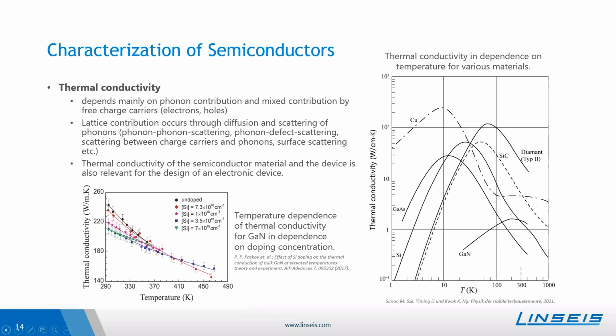In general, the thermal conductivity strongly depends on the doping concentration and also on the temperature, as shown in these two examples. So here you see the thermal conductivity in dependence on temperature of gallium nitride, the intrinsic case, the undoped one, and the doping with silicon. Here you can see that the intrinsic one has the highest thermal conductivity, and dependent on the doping concentration, the thermal conductivity can drastically change. Also, one can see a clear dependence on temperature. So this is why it's also important to perform a temperature-dependent analysis.